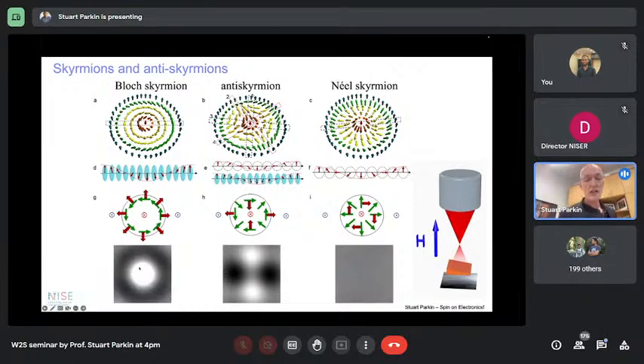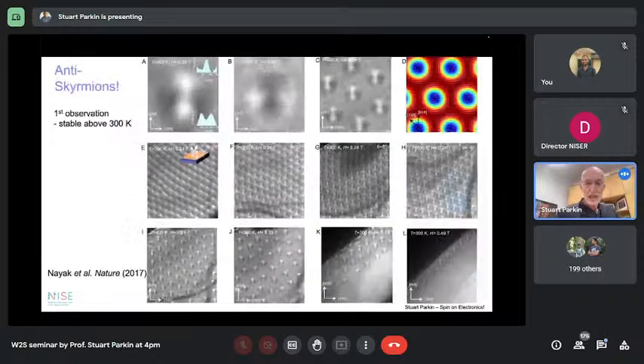We don't see a single white blob as for a Bloch skyrmion. We don't see nothing as in Néel. We would see this clover leaf: four blobs, two white blobs. That means the electron beam is deflected away from the object to the top and bottom, and two regions shown in black where the electron beam is decreased in intensity. This we can calculate by micromagnetic simulations and something called the transport of intensity equation, TIE. This is what we did, and this is what we saw.